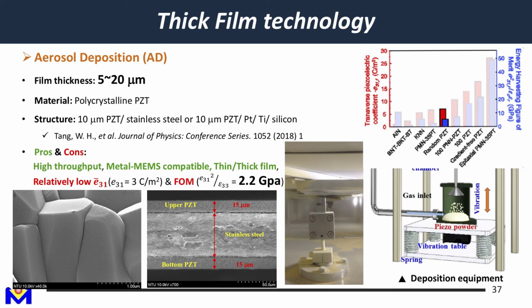Okay, so this is actually the figure of merit on the blue axis for different materials, and this is the piezoelectric constant. Here we are talking about aerosol deposition. This was originally invented by a Japanese researcher about 20 years ago. We can grow thin thickness around 5 to 20 micron, and it's actually a physical deposition method. You can see from the animation.